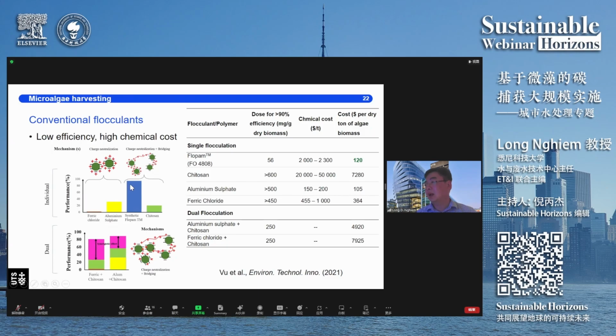recovering the microalgal biomass. So we look at a number of techniques that are available, and obviously flocculation is the most simple and effective technique for large-scale operation. We then check a number of different coagulants, inorganic coagulants as well as organic coagulants, and we see a very clear picture that has emerged. Inorganic coagulant is not very effective, and polymeric coagulant itself is also not effective unless it is cationic and highly charged. And that is because in order to effectively flocculate the microalgae, we need two things. We need to neutralize the negative charge of the microalgae, and we need to have a polymer that is of sufficient molecular weight so that it acts like a spider web to capture all the microalgae individual cells and aggregate